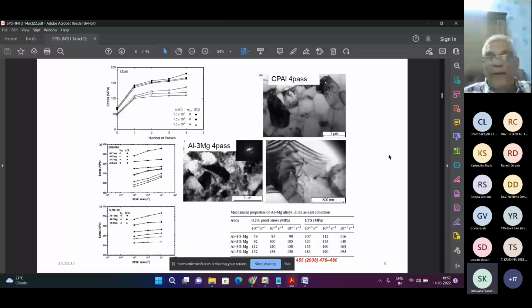And after four passes, we have taken the TEM image and tried to see whether the grain size has been reduced or not. You can see that the grain size is drastically reduced, less than 1 micron, whereas the dislocation fringes can be seen. In the left and right images you can see very nicely the dislocations, and you can also find out the distance between each dislocation.